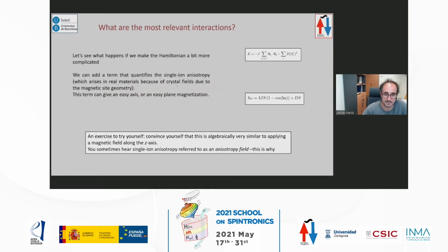Okay, another exercise. I won't do anything here. Let's see what happens if we add something else into the Hamiltonian, and just consider an anisotropy. So this is a magnetic anisotropy. You can do the same chain, and you just take this term that depends on the spin. There are no neighbors. If you do that with the same procedure, you will get that the frequency is the same term we got, plus a constant that depends on the strength D of the single-ion anisotropy. And that means that this magnetic energy is just lifting the frequency.